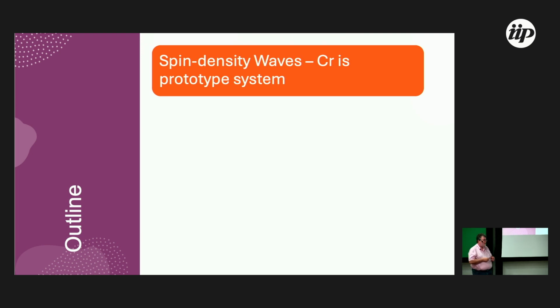The first studies using neutron diffraction in the 50s were applied to magnetic systems, applied to chromium, and discovered the particular type of magnetism of chromium. Antiferromagnetism in chromium was predicted in 1936 by Néel. Louis Néel proposed that chromium is an antiferromagnetic system, the first observation of an antiferromagnetic system. And during the 60s, the characteristic of the spin density wave was observed in neutron diffraction.